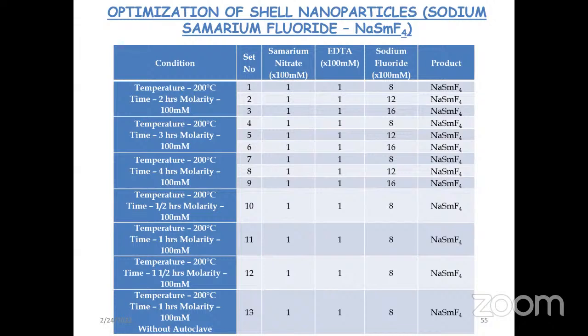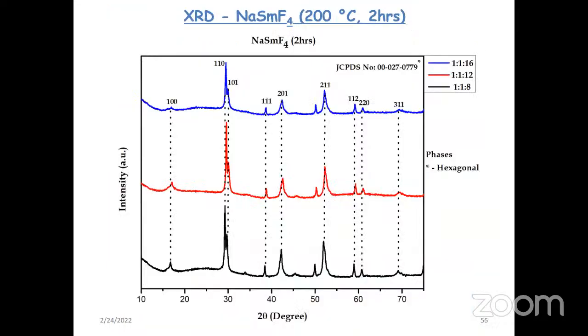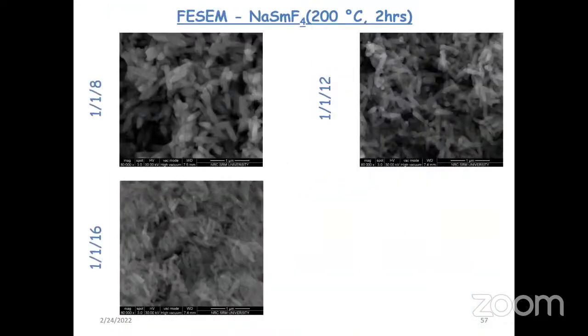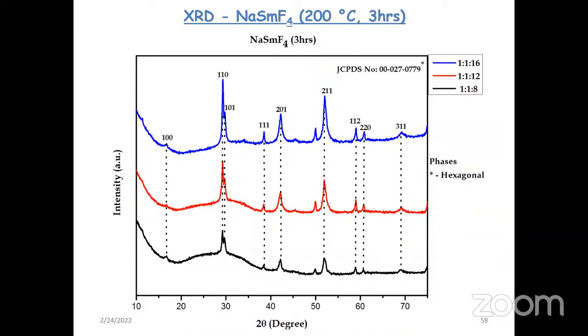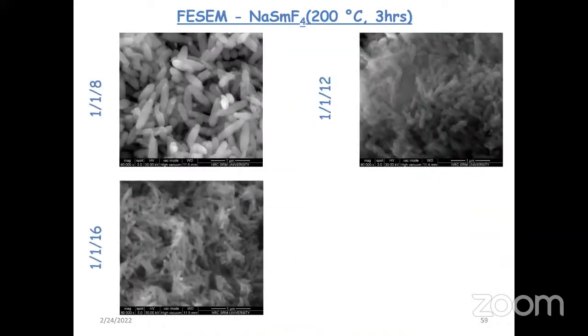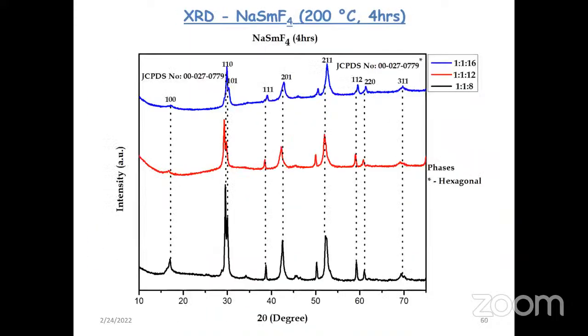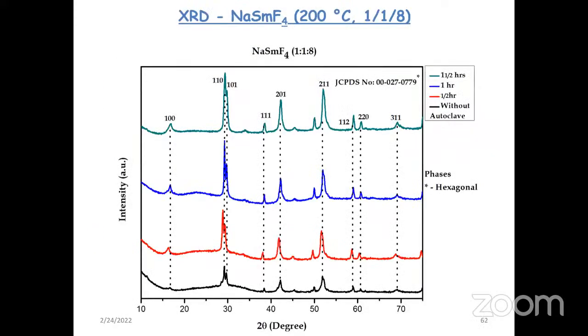Next, once we optimized the core, we also went for the shell optimization. For the shell, we utilized sodium samarium fluoride, where we used samarium nitrate and sodium fluoride to make that shell. Similar kinds of studies were carried out by XRD, and we used SEM to identify its morphology and phase analysis.